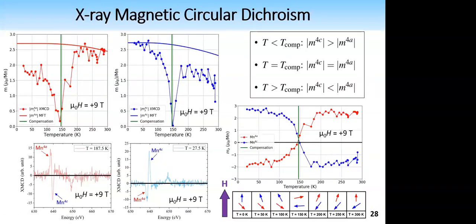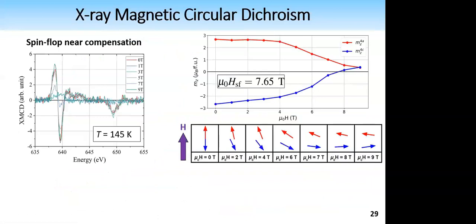Next, looking at the spin flop near compensation. Here we can see that compensation occurs at around 145 Kelvin in 9 Tesla. The first thing is that these curves probably don't remind you of the behavior of antiferromagnets. This is because here we are close to compensation. The net moment is not completely zero. There is a residual moment and some anisotropy, so we have a much smoother spin flop transition than what is observed in antiferromagnets.